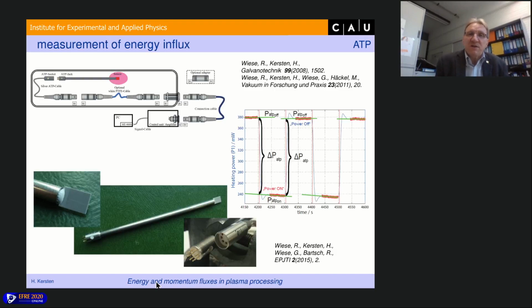And as I mentioned, we have two methods. One is the active thermal probe, and I just want to shortly mention how it works. As you can see here, this is the probe, and you can insert the probe by a feed-through to your reactor, to your plasma, and it's very simple. You have to heat this sensor area. For instance, here it is heated to a certain temperature.